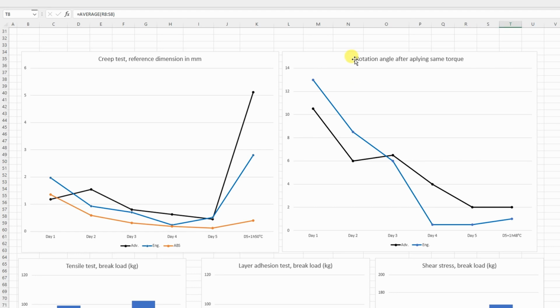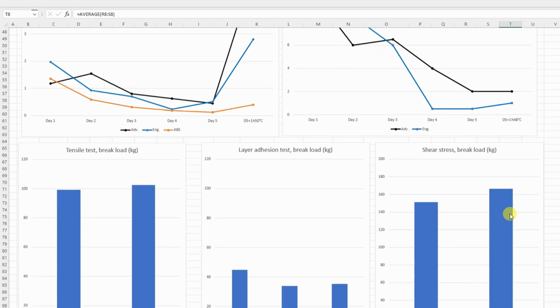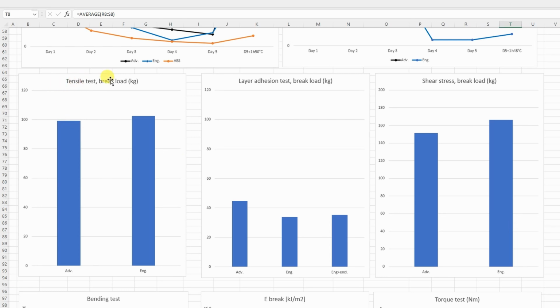On a rotation or screw creep test, I can see that it slows down with the creeping. Interesting, on the third day, which was the hottest day, 36 degrees Celsius was the max. Maybe that's the reason why we have additional bigger creeping here of the advanced PLA. But basically after the fourth day, it almost stopped creeping, and even inside the oven, at 50 degrees Celsius, it didn't have additional creeping. On a tensile test, the difference was very low.